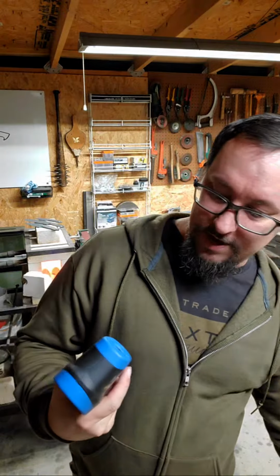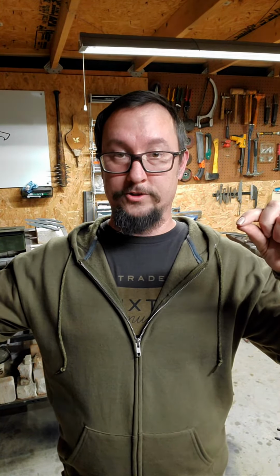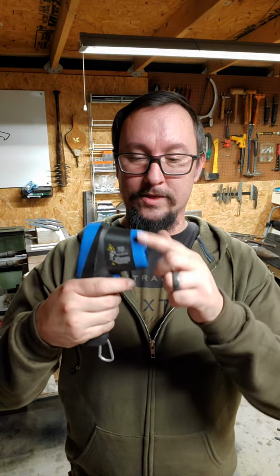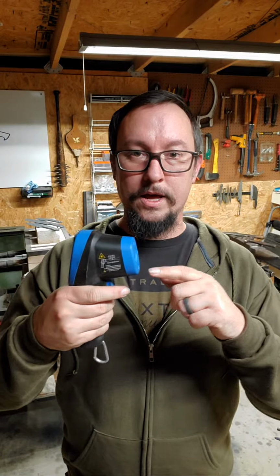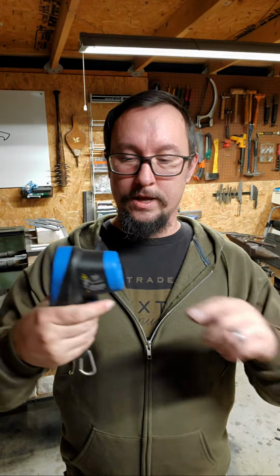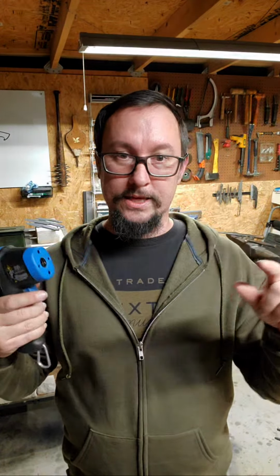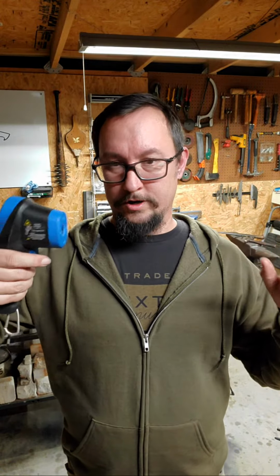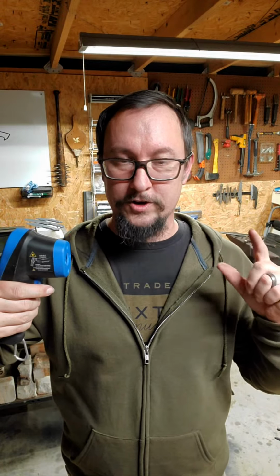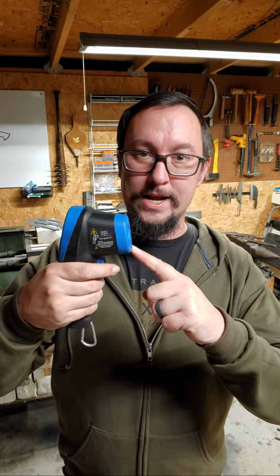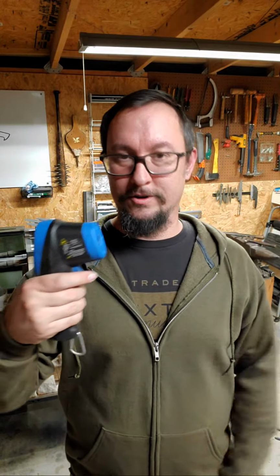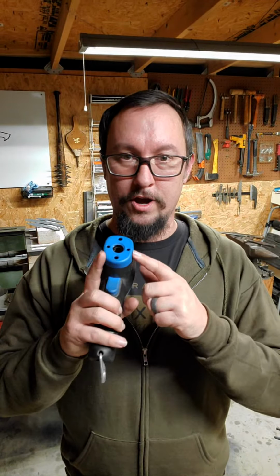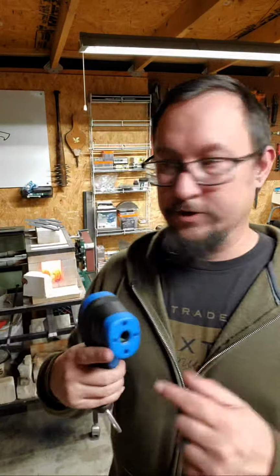What'll actually happen is there's going to be two little laser dots that come out of this. They actually cross and intersect at one point. If you just check it where they cross over, you're great. But if you get this too close to a heat source, this plastic will heat up, and it can heat up to 100, 150 degrees. And if this blue piece is hot, it will throw the temperature off of the thing that you're actually checking. It'll say that your steel is 100 to 150 degrees warmer than it actually is, because it's reading the temperature off of this on top of the temperature of the material you're working with. So you want to hold it away, make sure it stays cool, so that the temperature of the laser gun itself doesn't affect the temperature of what you're actually checking.